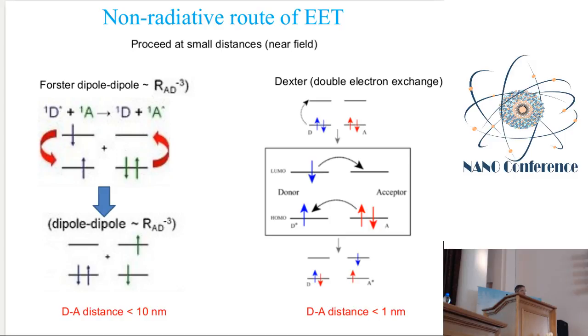For the Forster dipole-dipole interaction, we should have a distance of less than about 10 nanometers. And for Dexter double electron exchange, we have practically physical contact between donor and acceptor, where the donor's excited electron is transferred to the acceptor, and the acceptor provides a ground state electron to the donor. So I will speak only about Forster resonance energy transfer, because I will consider molecules which are not in physical contact, but at some distance from each other.